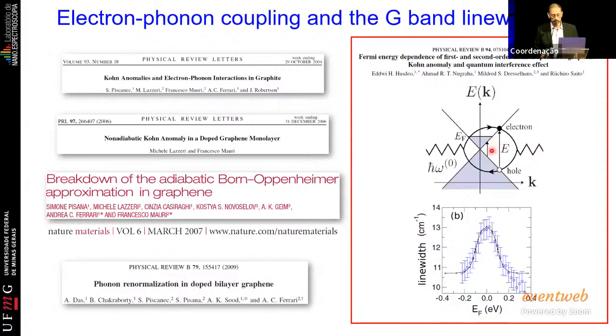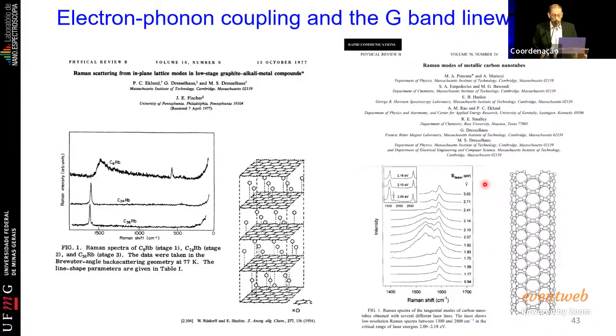electron hole interaction. So what happens is that if you dope the material positive or negative, the line width will decrease because you kill the possibility of the phonon decaying into an electron hole pair, and you increase the lifetime and you decrease the line width. Okay, when this was shown in, as I said, 2000 something, it shed light on a lot of phenomena that we already knew in carbon materials, but we didn't fully understand.